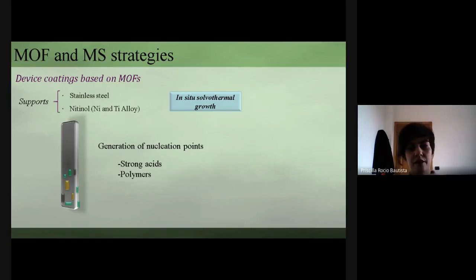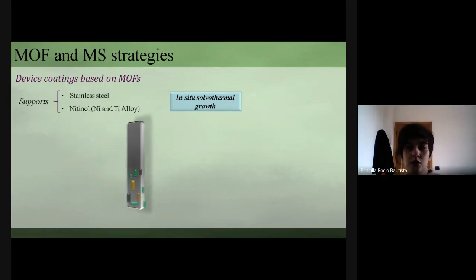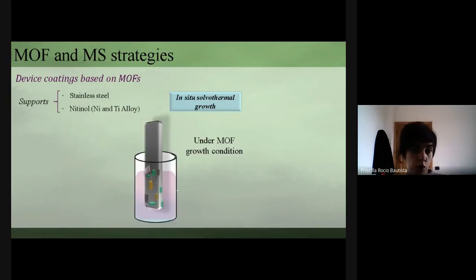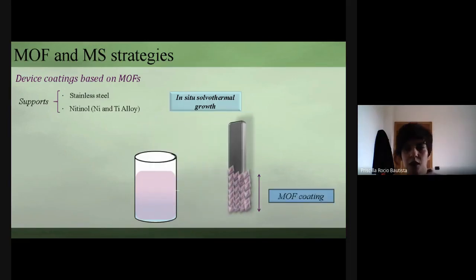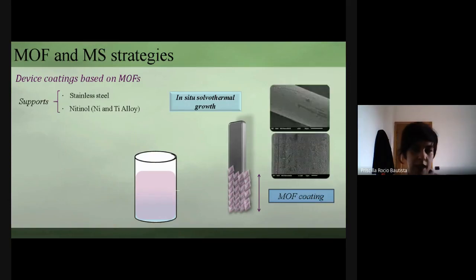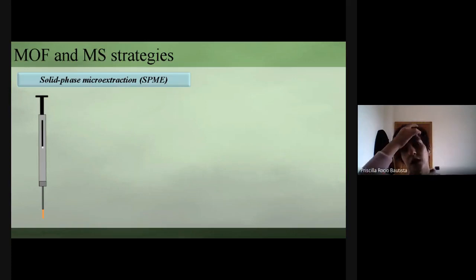generating some imperfections and ruggedness. The other option is a polymeric treatment, normally with APTES, where the siloxane and long chain favor the MOF anchorage. After that, the second step is the MOF growth under the proper solvothermal conditions. In the slide, I include a scanning electron microscopy image corresponding to MOF coating devices.